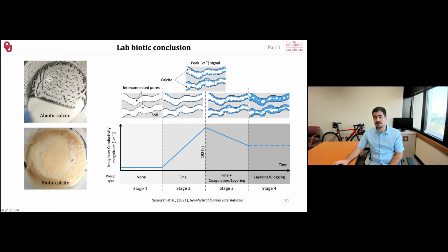Using microbes, on the other hand, you can clearly see the precipitates are homogeneously distributed. We have almost no empty spot like this one. This one, I don't consider it. Probably it's just a crack or something. But comparing this to just using chemicals, we can clearly see how much more beneficial it is to use microbes. They carry the calcium with themselves. They precipitate it everywhere at the same rate.